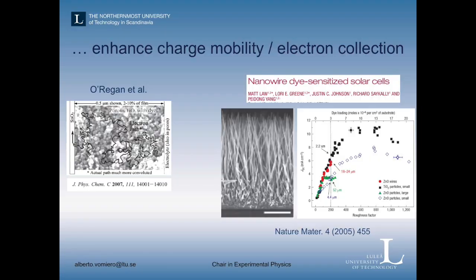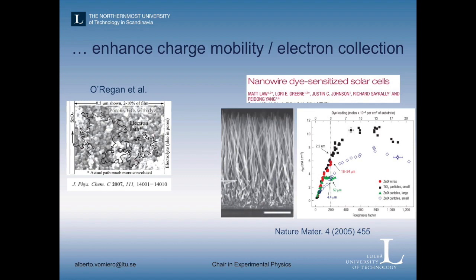Another way in which nanomaterials are very important is, for instance, by using elongated one-dimensional structures. It's pretty clear that when you use mesoporous materials and you have to collect charges, that's a very challenging process, because the charges are hopping from particle to particles, even several thousands of times. So in 2005, Professor Peidong Yang from Berkeley was proposing, why don't we use this elongated structure? At the beginning, it was a pioneer in the growth of these nanowires. Now it's pretty consolidated